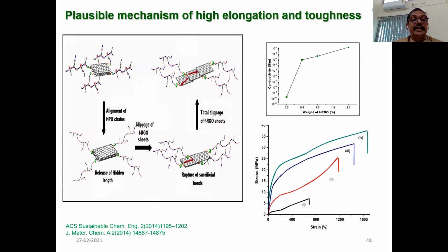This is explained by the release of hidden length and rupture of sacrificial bonds. The functionalization results in covalent linkage of the graphene oxide with the polymeric chain along with non-covalent interaction. When low external force is used, the hidden length due to this non-covalent interaction is released, and that increases the elongation. Further, rupture of the sacrificial bond and slippage of the layers of graphene resulted in high elongation, while strength is also improving.